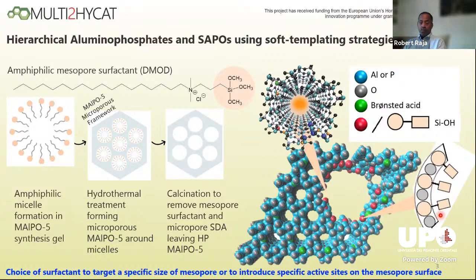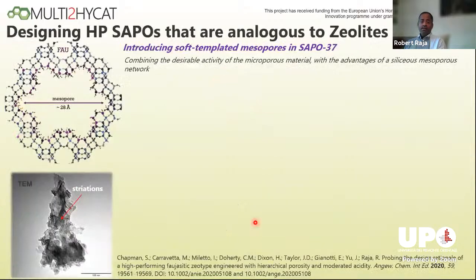One of the problems which one sees with other methods, when you use ionic methods or you adsorb organometallic entities, is the propensity for leaching. But with this covalent strategy, we set out to achieve more solid, robust catalysts, which could be amenable for industrial validation. So just to give you an example of a recent paper we published with colleagues in Alexandria, we have designed this hierarchically porous SAPO catalyst.